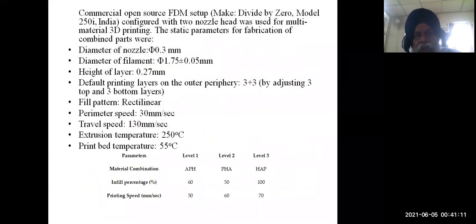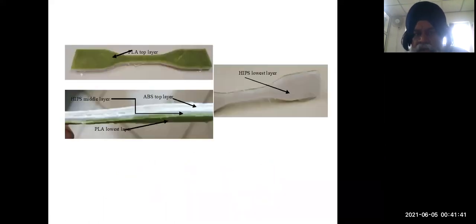So we tried to print it on an open source FDM system by keeping some parameters constant, like diameter of the nozzle, diameter of the filament, layer height, default printing setting, printing pattern rectilinear. So these parameters were kept constant. What we actually varied is, in one case we put the lower layer of ABS, then in another case the lower layer of PLA, then in another case the lower layer of HIPS, and we tried to use some DOE to see the effect with other parameters like infill percentage, printing speed. So you can see these are some of the tensile specimens as per ASTM D638 with the different topping of layer. And we try to see what is the effect.